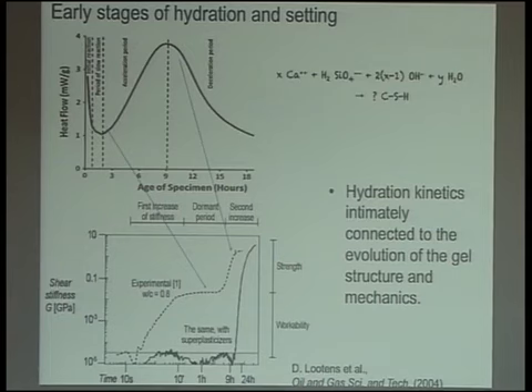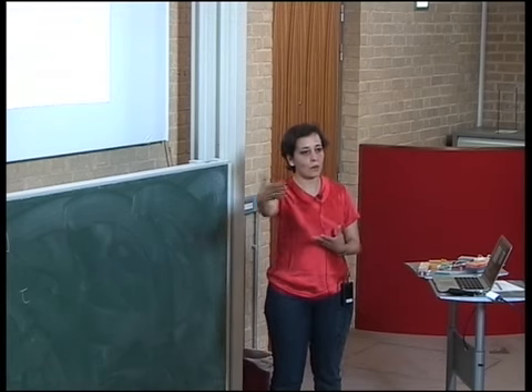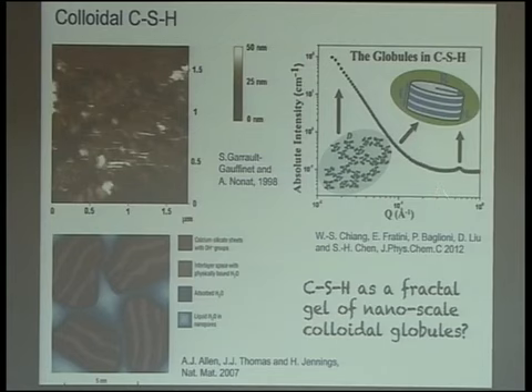One of the things that has been debated a lot over the years is what is the structure of this gel and how it develops and how it grows, because these are the things that you would like to control. And because most of the experiments have been done actually at the end of this hydration process, it's extremely difficult to figure out what leads you there. There are some traces, for example, from small angle neutron scattering, where you can see that there is a typical building block of this disordered structure, and people have proposed that, okay, it seems to be seen also in AFM images.